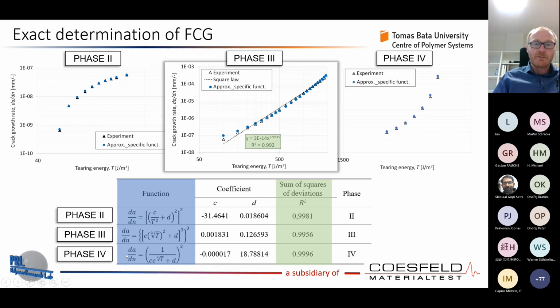So for the second, third, and fourth phases, these are some parameters for the functions, and here we can see the sum of square of deviations, R squared: 0.998 for the second phase, 0.9956 for the third, and 0.9996 for the last one. What we wanted to see here is whether it is enough to use a power law, or whether there is a need to use another specific function. And what we see is, in general, for this material, which is EPDM, the crack growth propagates really nicely, with very stable crack propagation, which would not be the case for natural rubber and others. However, we use this to get very precise data.